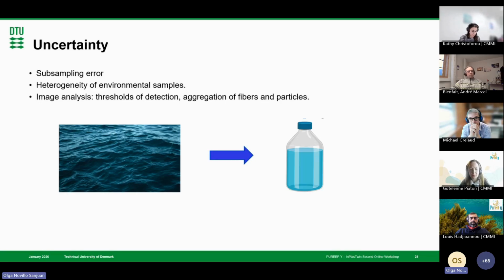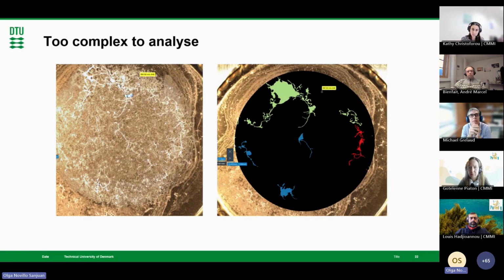And then in the LDIR specifically, although it's really nice for automatically detecting the particles, you need to be careful with the thresholds you put in the instrument with aggregation of fibers and particles, because as with every image detection algorithm up to now, it still struggles with separating the fibers, for example, or the particles when they are clumped together. You will see an example now. So here, this filter was too complex to analyze. This sample should have been either divided in two or further diluted, because there's too many things going on for the instrument to detect them properly.